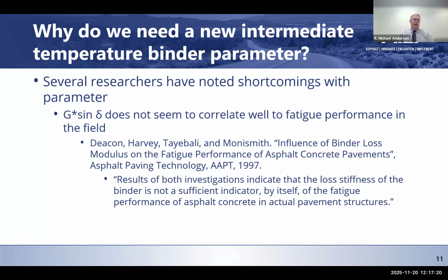If you go to a paper in 1997 by John Deacon, John Harvey, Akhtar Tayabali, and Carl Monismith, they talk about the influence of binder loss modulus, which is G* times sine delta, on fatigue performance. And what they noted was that the loss modulus, or the loss stiffness, of the binder is not a sufficient indicator by itself of the fatigue performance of asphalt concrete in actual pavement structures.